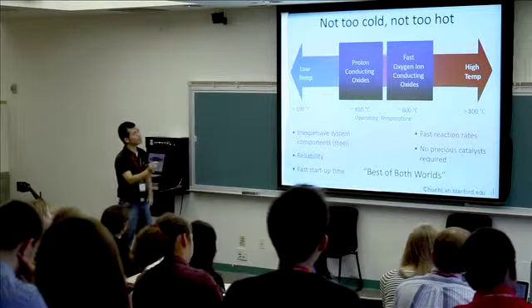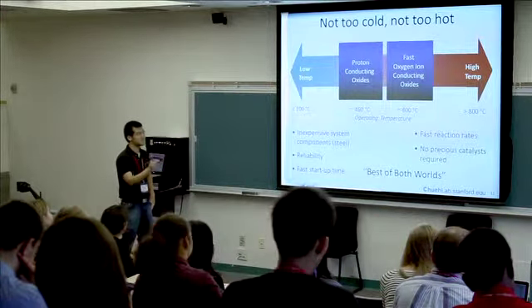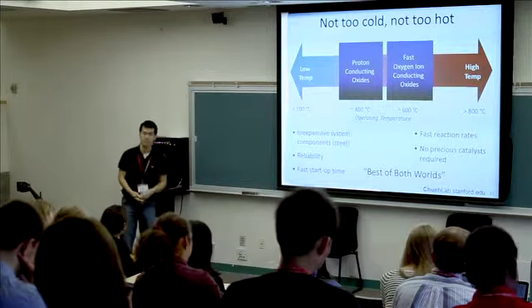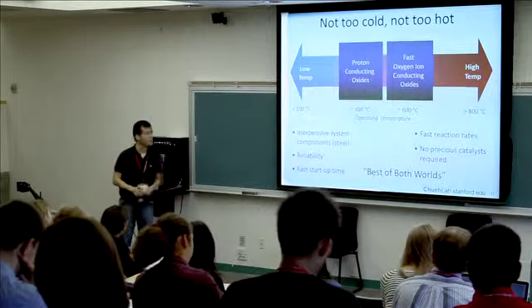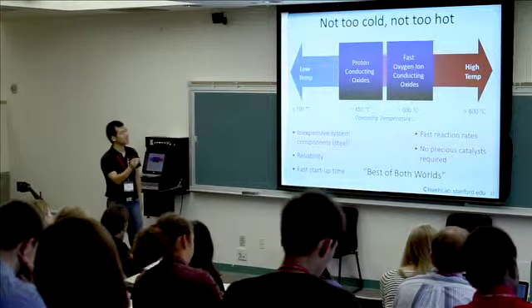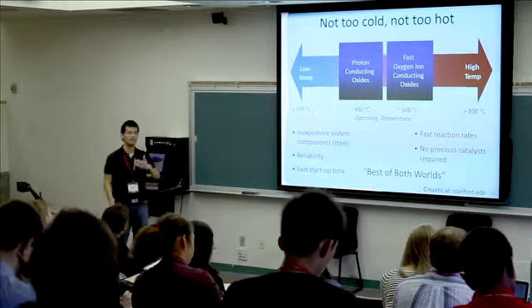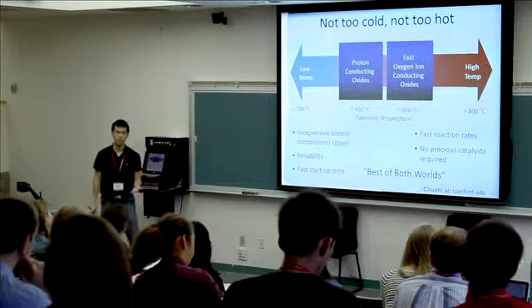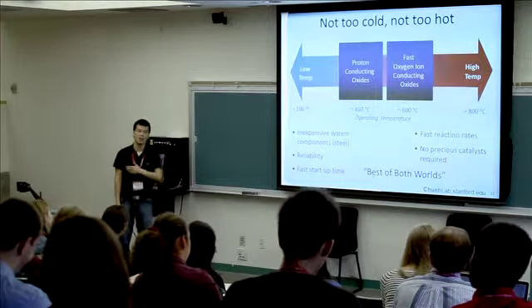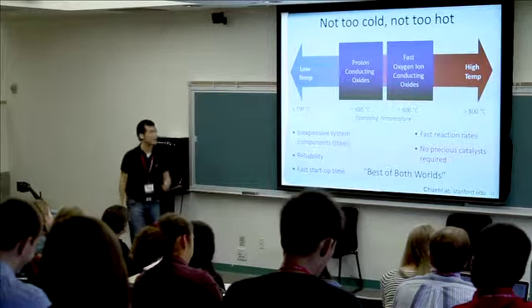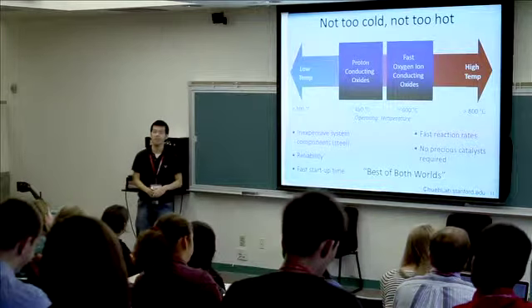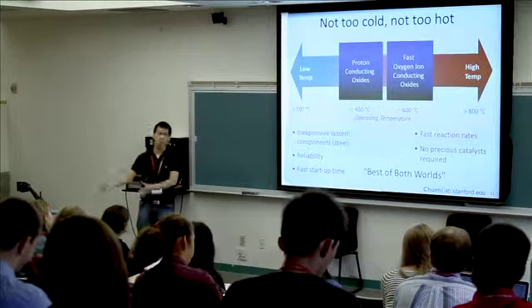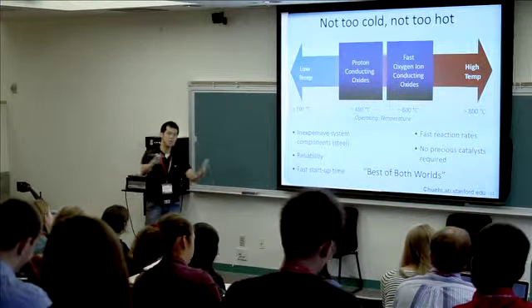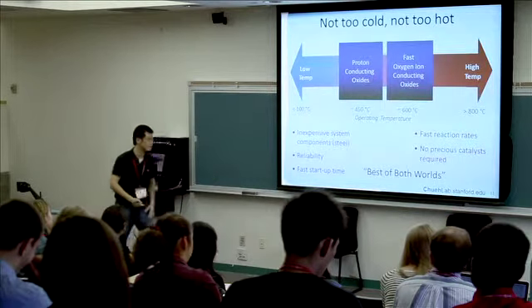And some of the materials we're looking at are fast oxygen ion conducting materials. So these are oxides that you can take oxygen ion through very quickly. We're also looking at a proton conducting oxide, which is the ceramic analog of the polymer electrolyte. So here you don't need the water to carry the proton, but the proton is in a purely solid state manner. So essentially it's proton hopping from position to position within the material, from site to site.